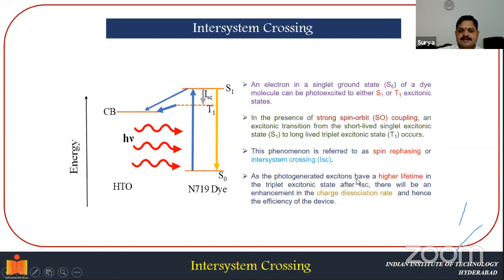The photogenerated excitons have higher lifetimes in the triplet excitonic state. In comparison with the singlet excitonic state, the triplet excitonic state has a long lifetime. For instance, if an electron goes to the singlet excited state, it will spend very little time and go to the conduction band of the semiconducting material. However, if an electron goes to the singlet excitonic state and further goes to the triplet excitonic state, it can spend more time there and then go to the conduction band. Now the question is, what is the advantage of spending more time in the triplet excitonic state? The advantage is that one can enhance the recombination time. If electrons go to the triplet excitonic state, they spend more time without recombining. As a result, the efficiency of the device can be enhanced.